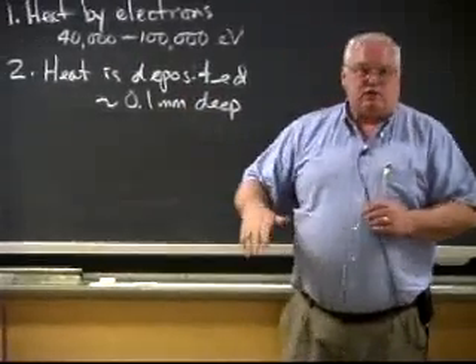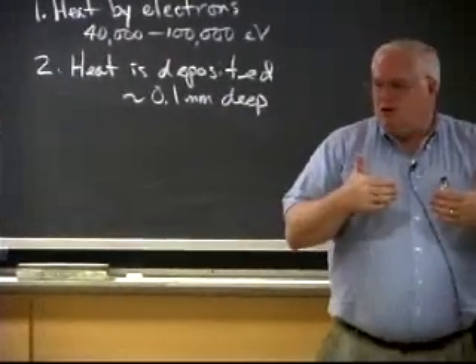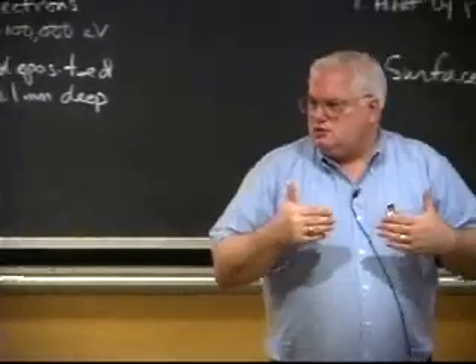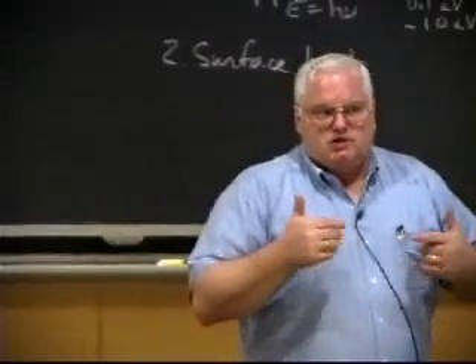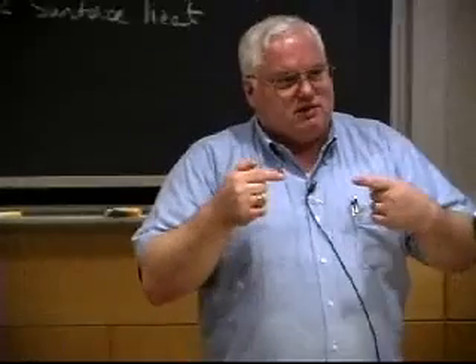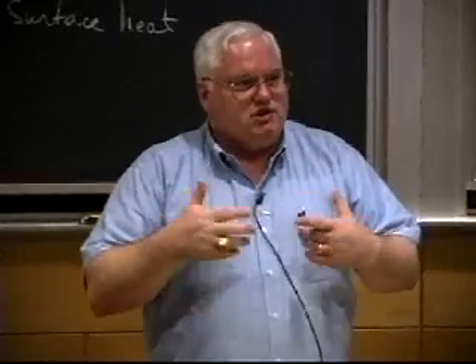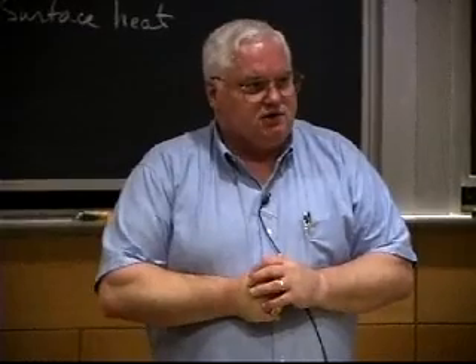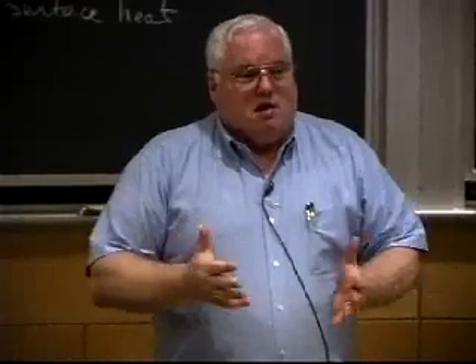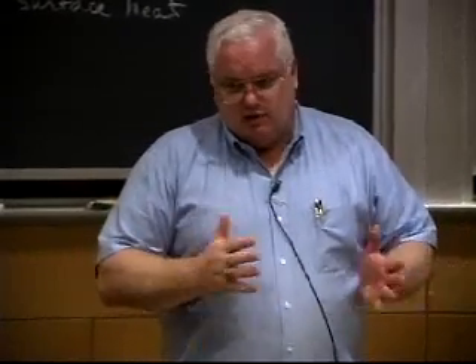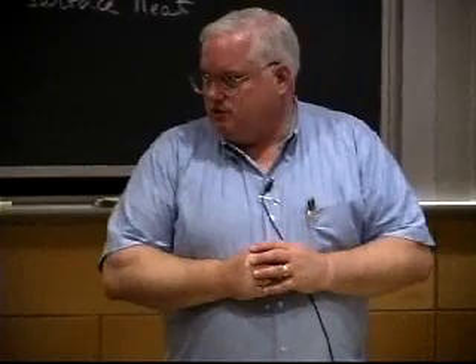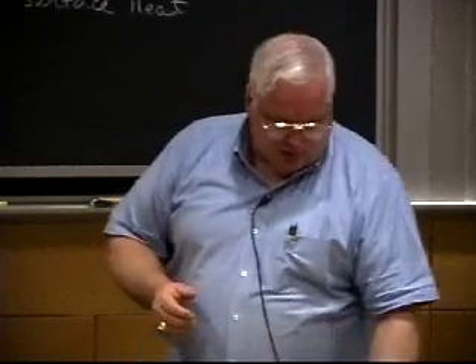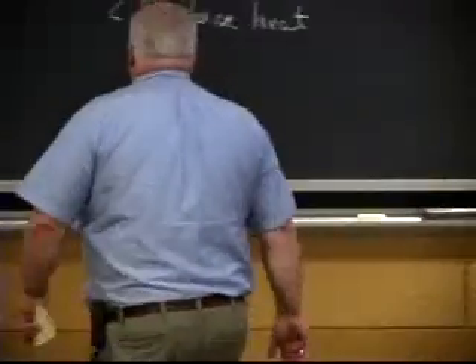You go over here to this process, now the maximum heat is 4 thousandths beneath the surface, and so that gives me compressive residual stresses when I'm all done, which is favorable for the fatigue situation. So two high heat intensity processes give you completely different surface residual stresses because of the difference in the energy of the particles that are hitting.